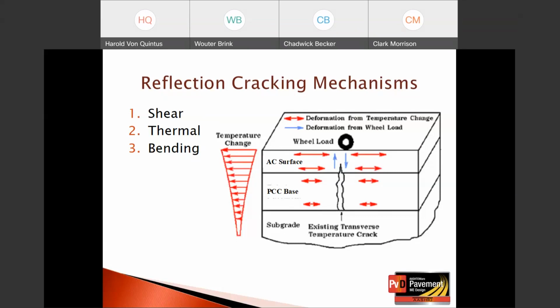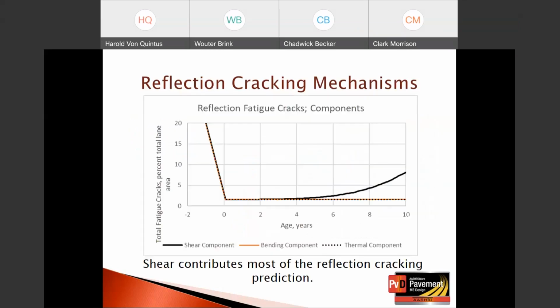And then the thermal, and that's simply the horizontal movement of the concrete base and/or asphalt layer that causes tensile strains above the crack in the concrete and/or asphalt base in the asphalt overlay itself. Now, to identify the most important of these 3 components, shear, bending, and thermal, which one is the most important, or are they all three significant?